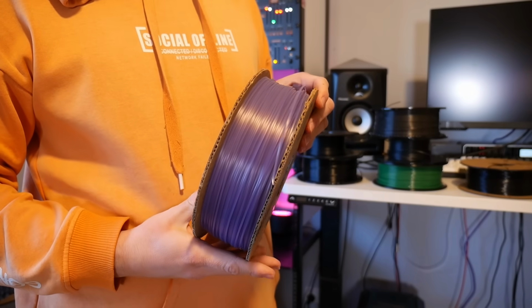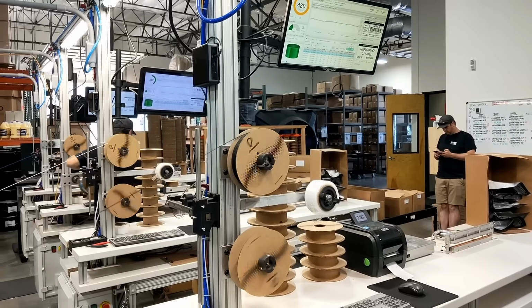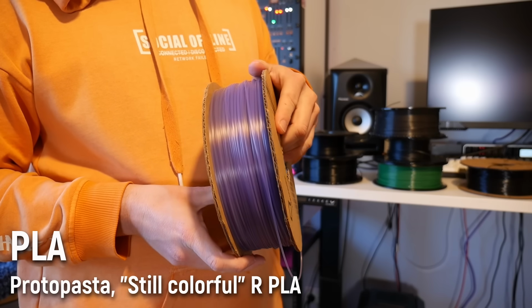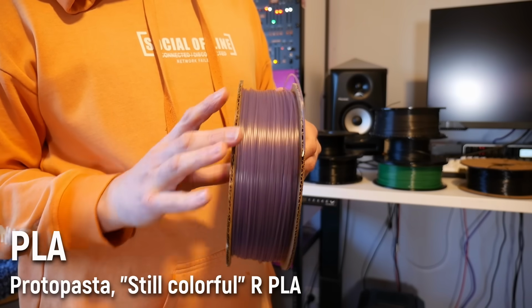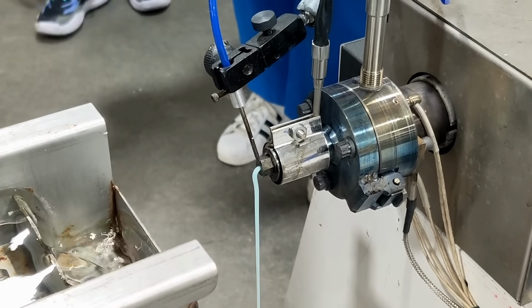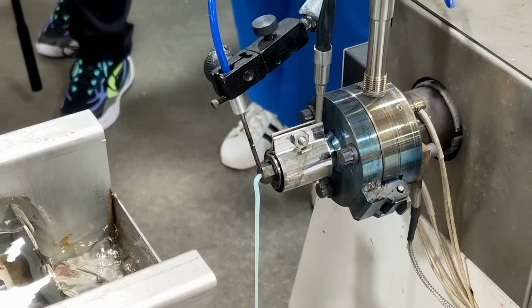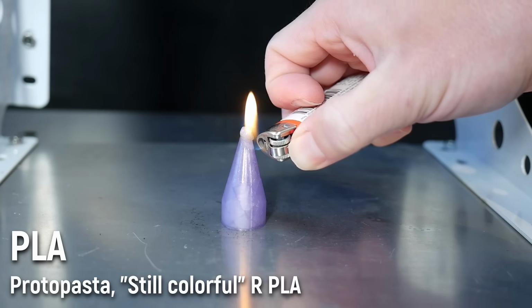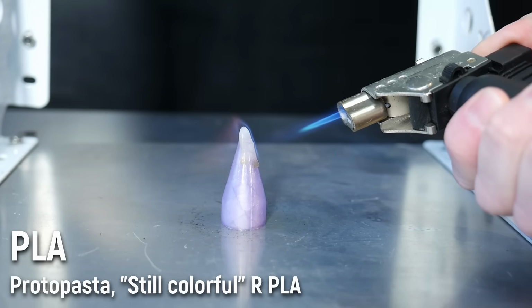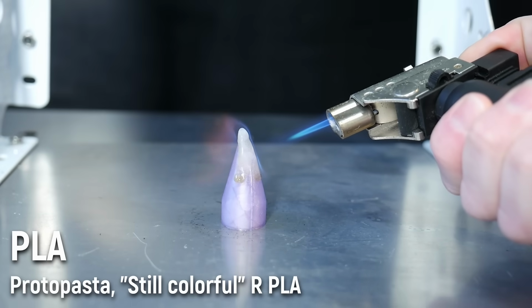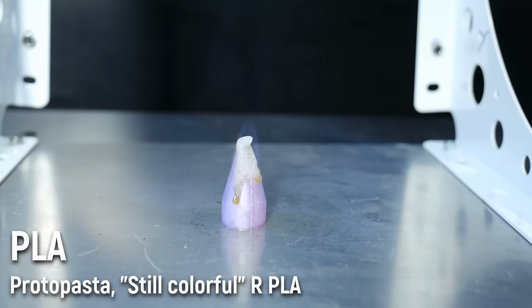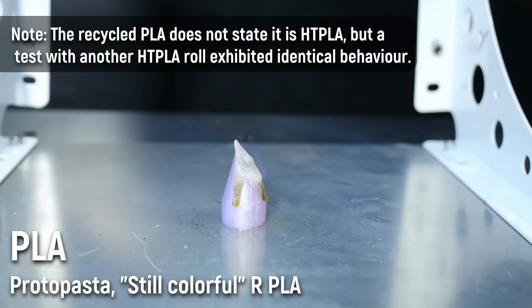The final PLA I tested was this special roll that I picked up from Protopasta when I visited them back in 2023. This is a, quote, still colourful spool of HT PLA, which is Protopasta's way of reducing waste by saving the molten plastic that's used to purge the extruder lines between different colours. It didn't want to burn with a lighter, but with the blowtorch, it kind of sustained a similar flame to the Prusament PLA, a barely visible blue one, but it didn't last nearly as long. The print also seems to live up to its claim of being HT, or high temperature, and this is even without any annealing, because it didn't seem to deform quite as fast as the Prusament PLA when being blasted with a blowtorch.